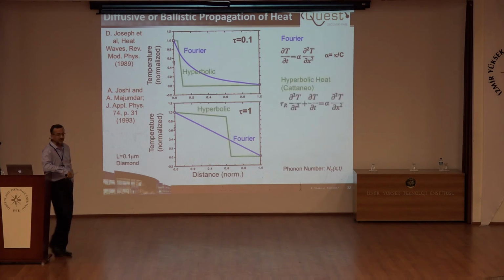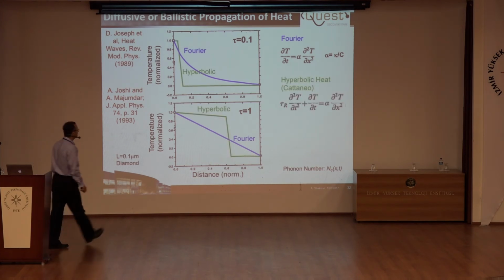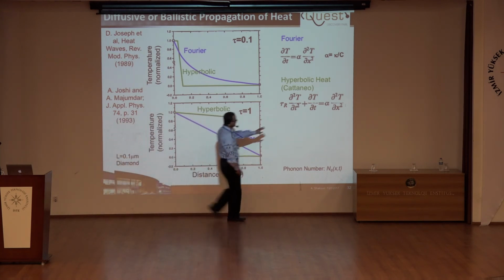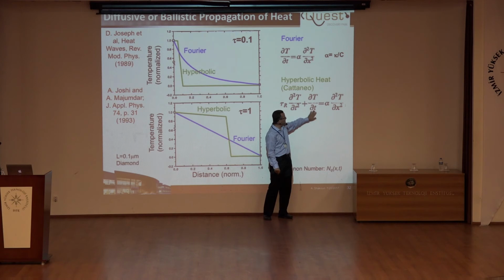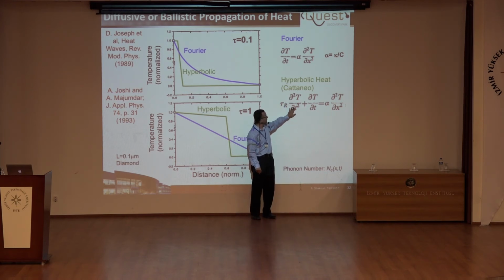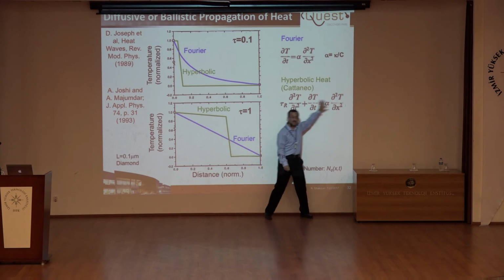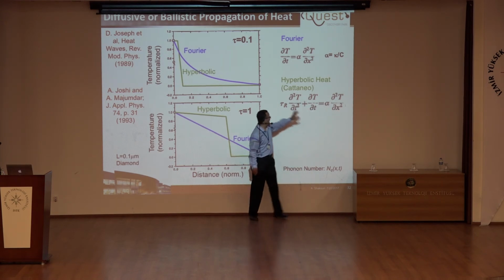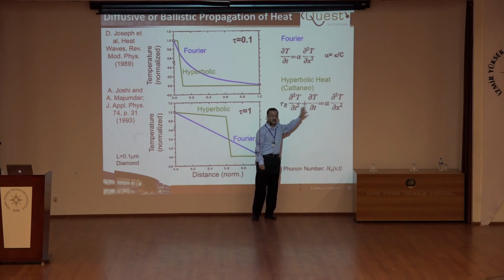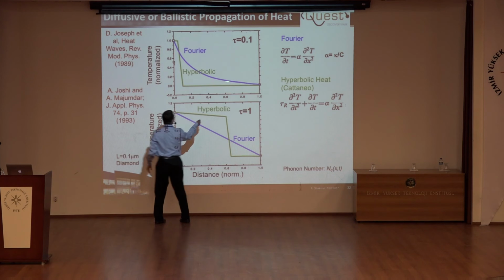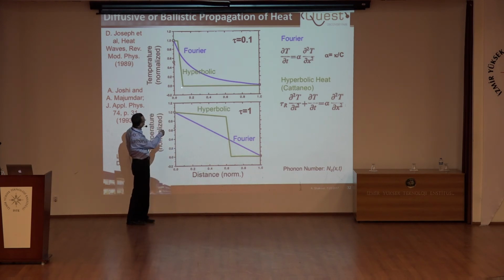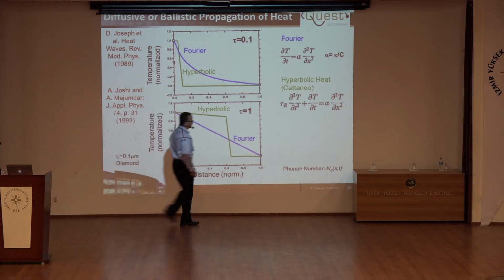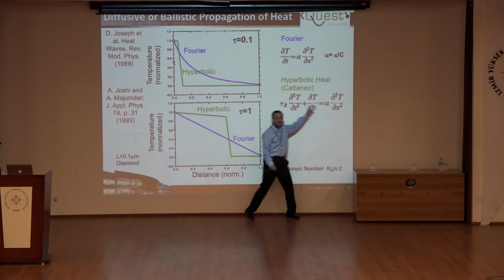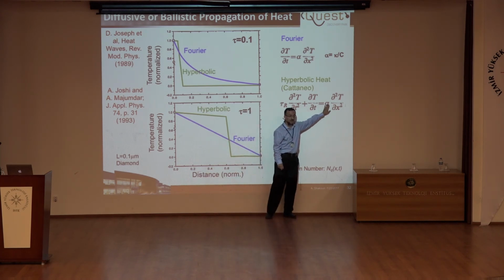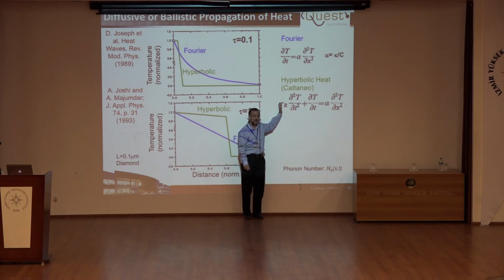Well, if you're a mathematician, you cure things by adding terms to the differential equation. So Cattaneo and people said, in addition to the first derivative of temperature with time, let's add a second derivative of temperature with time. Second derivative with time, second derivative with space give you a wave behavior. Wave behavior, it's called a hyperbolic differential equation, has a finite speed, and this is the temperature you calculate. At early times, temperature has only gone to this distance, later time, this distance. What is interesting is the original equation had only one parameter. You just added one more, but it's very physical. This parameter described diffusion. This parameter described the speed of wave propagation.